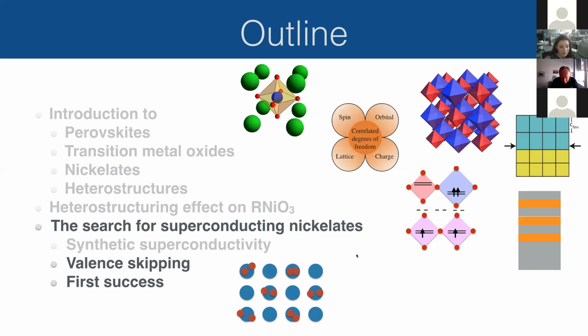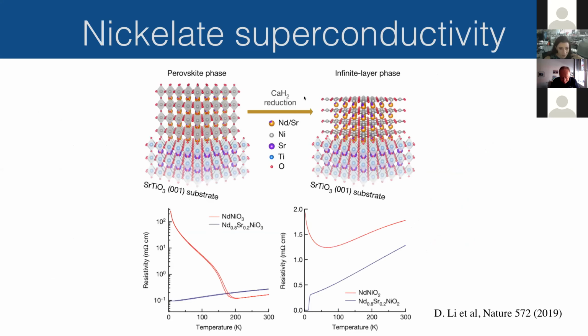Okay, last thing, the first success, the first superconducting nickelate. All I have talked about so far is perovskite nickelates. It turns out that the trick was to not look at perovskite nickelates. So what happens is that the infinite layer phase of the rare earth nickelates has recently been discovered to be superconducting. So here is just a sketch of how they achieve this infinite layer phase.